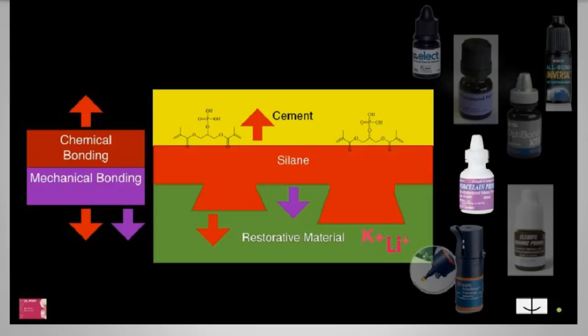If you want to extend that shelf life, you can do 2 things. 1, keep it refrigerated. 2, you can actually order the A and the B primer separate. And then when it's time to prime your restoration, then you add the A and the B together, mix them up, and prime the ceramic. Now, the advantage of that is that if you keep them separate, those are good for a very long time. The shelf life is very far extended. You don't have to really worry, is it still going to be good? It's going to be good for a long time. So that's my take on porcelain primers.